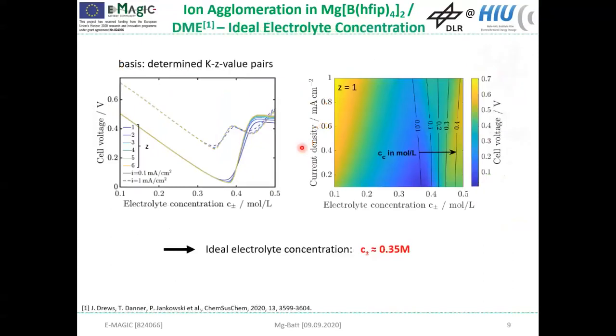And now that we know value pairs for K and Z, we are also able to identify the ideal electrolyte concentration. So here you can see the cell voltage in dependence of the electrolyte concentration for 6 different K and Z value pairs and 2 different current densities. And thereby this minimum indicates the ideal electrolyte concentration where we have the smallest overpotential.